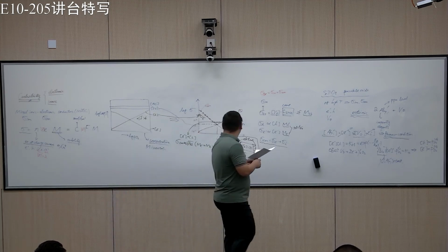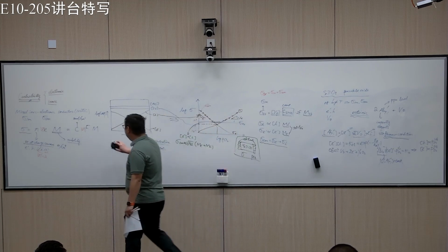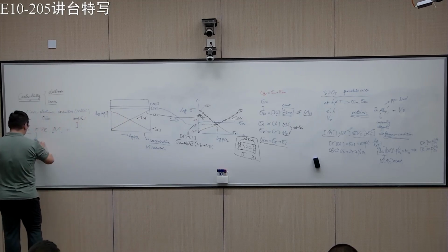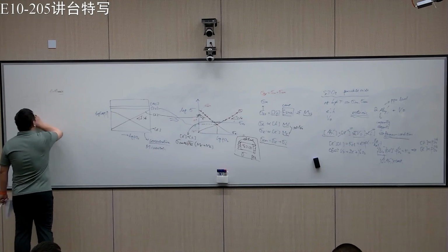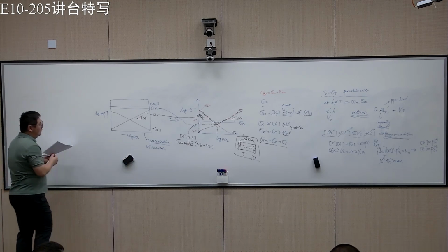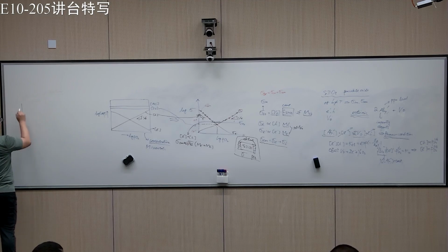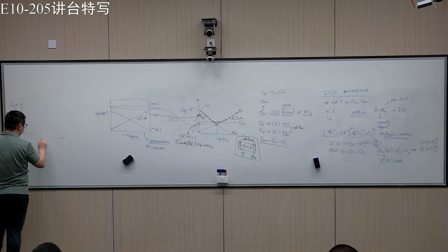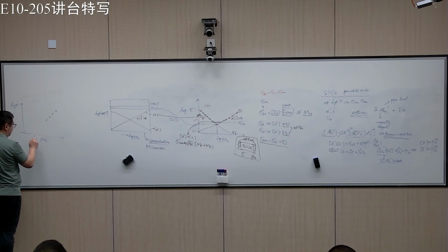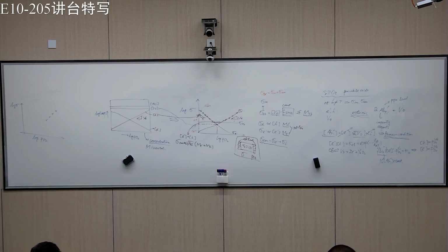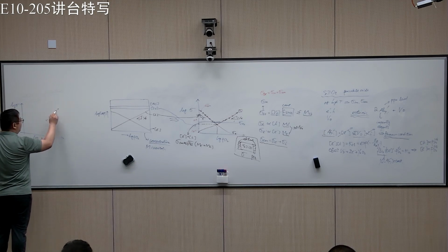Okay, so basically when you do your experiment, when you measure the conductivity as a function of pO2, you get a function of the data point here. So again, this is in the log plot. So then you can say, okay, I connected both, then it's 1/4.